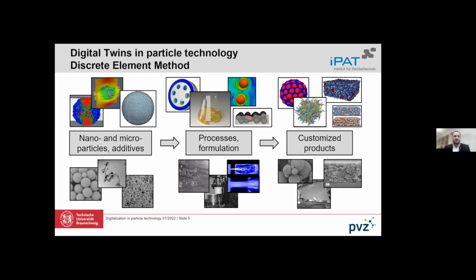Or we can have 3-phase simulations with an air phase, a fluid phase, and the solid phase in a laminar way, as in this drying simulation, for example, or in the middle we have here a 3-phase simulation with a very turbulent fluid surface containing also particles in this shaking flask. And at the end, we can deal with very complex product structures, but we can also use very complex particulate morphologies. Here, just to give an example, are some coatings from the electrode processing or from the spray drying, or you can even simulate very fractal filamentous microorganisms and their properties. The properties could be electrical conductivity, thermal conductivity, mechanical properties, structural properties, all these things we can nowadays simulate with the increasing computational power.